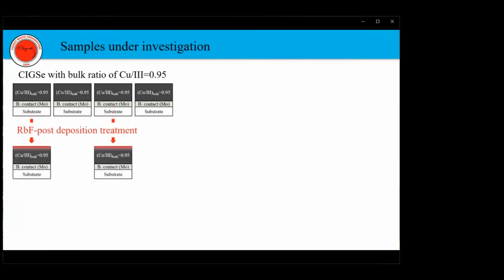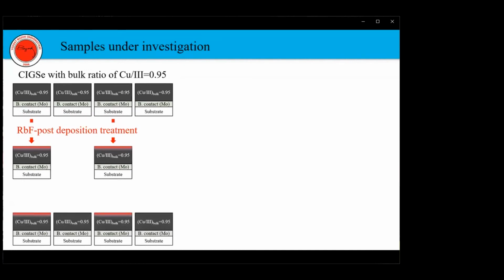Now, I would like to briefly present the samples under investigation. First, CIGS absorber films are deposited onto molybdenum-coated glass substrates using a three-stage co-evaporation process. The bulk copper to indium plus gallium ratio was adjusted to 0.95. Rubidium fluoride post-deposition treatment was applied onto 2 samples, whereas the other 2 were kept untreated. Then cadmium sulfide and zinc oxysulfide buffer layers were deposited onto treated and non-treated absorbers using chemical bath deposition. The treated and non-treated samples were dipped into the same bath of either cadmium sulfide or zinc oxysulfide.